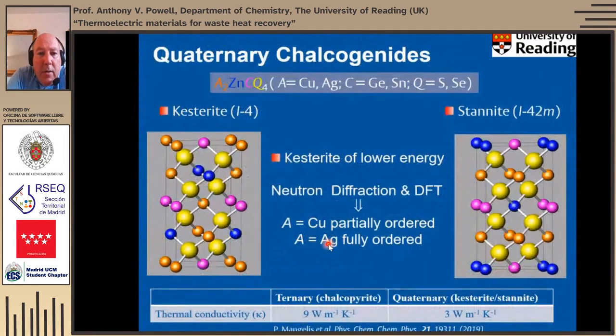So moving on from chalcopyrite, if we introduce not just 2 cations into the zinc blende structure, but 3, there are 2 principal possibilities, the kesterite and the stannite structure, which differ only in the way that the ions are ordered. So for instance, if this was an A site with copper in it, and the orange ones here are copper, in the kesterite structure, the copper are in every metal layer. In the stannite structure, they're restricted to 2 out of the 4 layers.